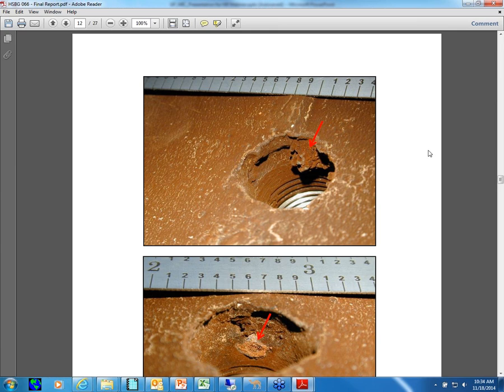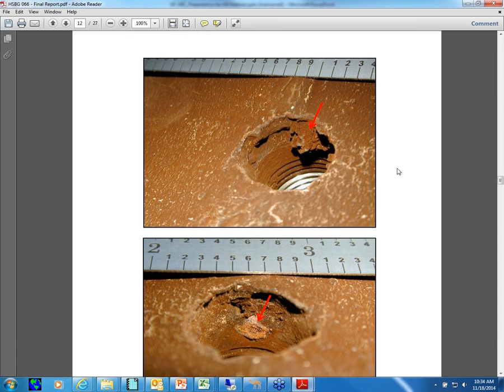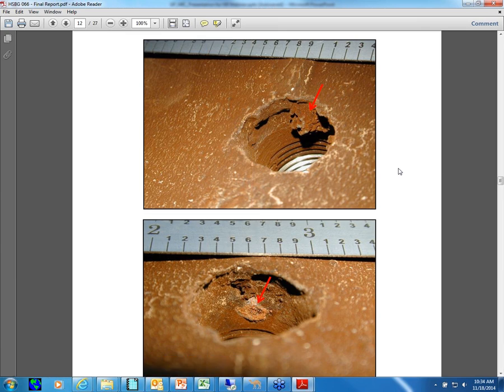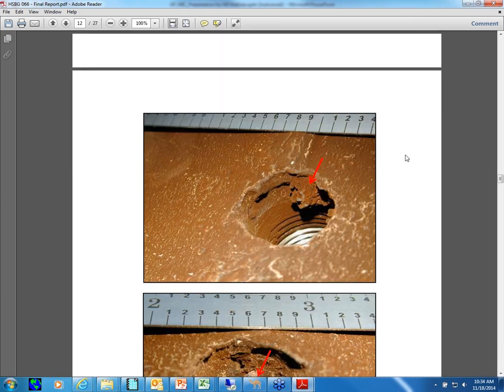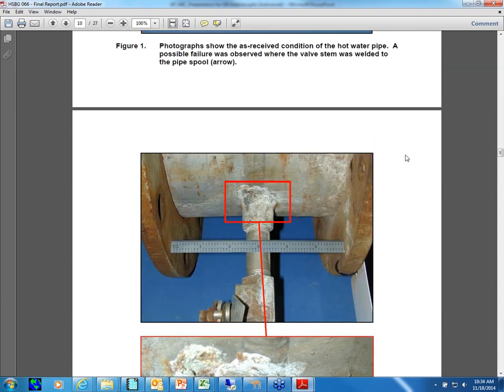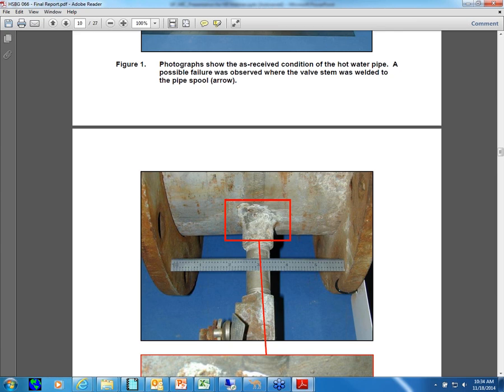Because like I said, in the early days, we were at early stages of identifying the problem. We had a lot of problems just trying to identify what we actually had. So this is a picture of a piping spool piece that came out of one of the mills in the hot water system. And we were trying to identify if we had MIC or not. So what we actually saw was a spool piece that had a leak on the weld, just like we saw in all the other cases.